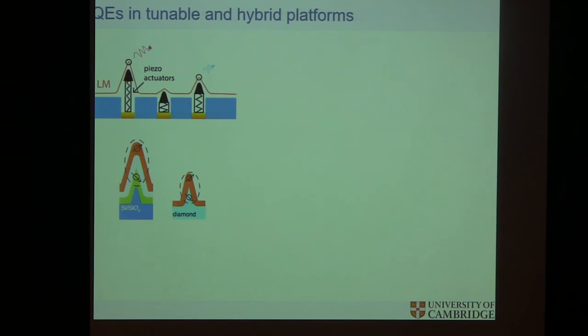Or you do it on a different material like diamond, where each pillar, which you can actually implant, each active spin or even a dark spin coupled to the exciton that is monolayers away from it. So this is the next thing that one can pursue, to have a coupled system of these structures.